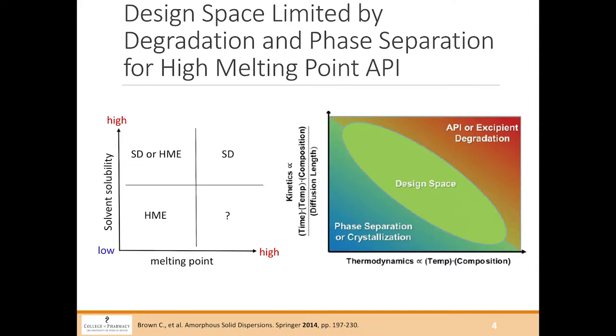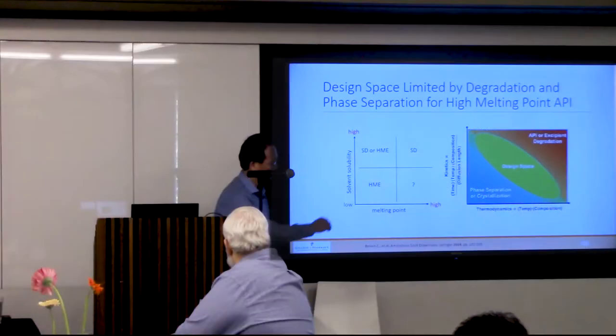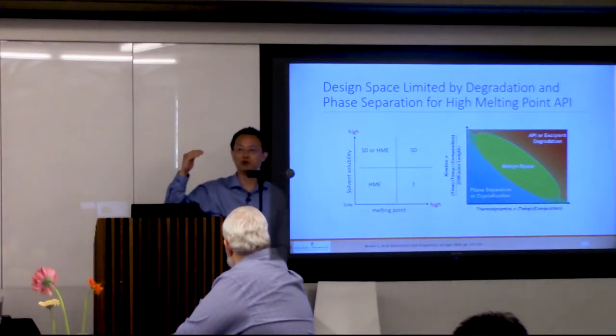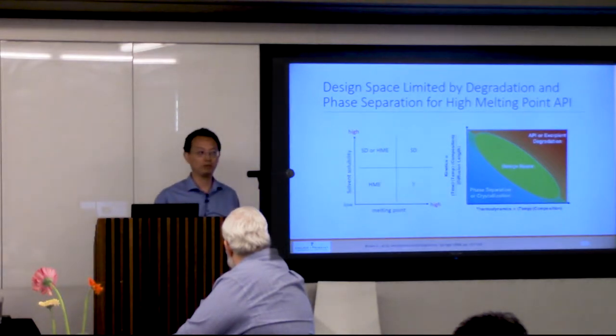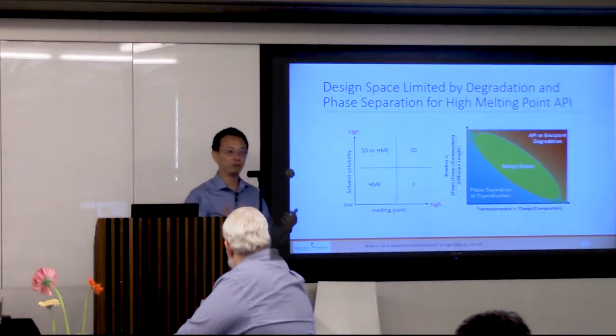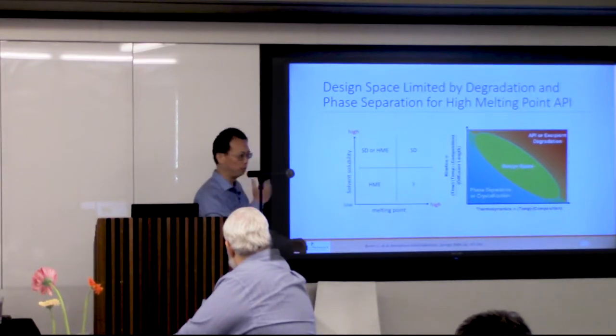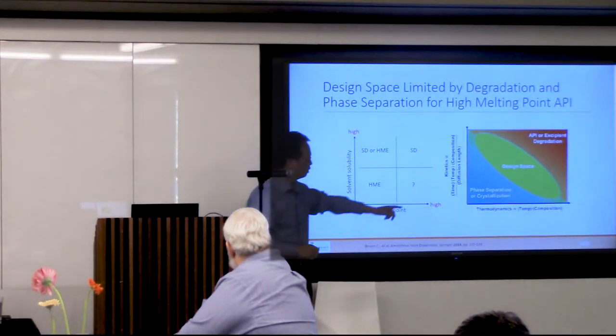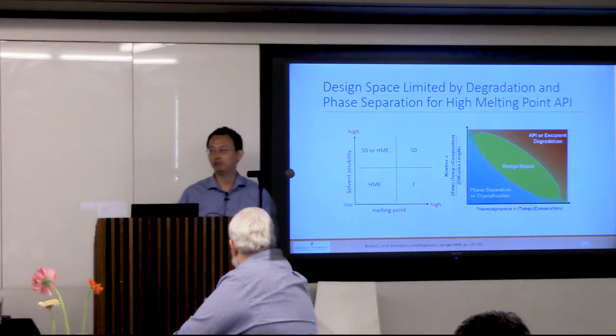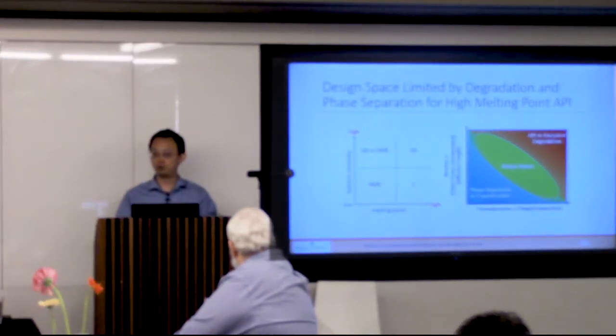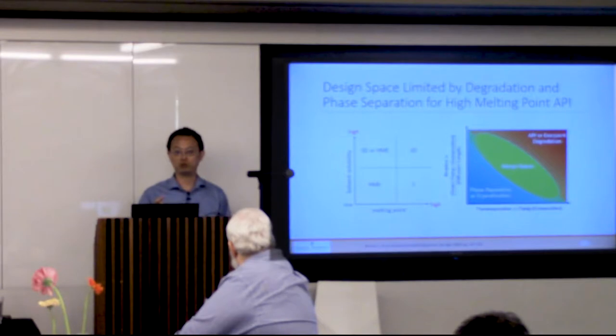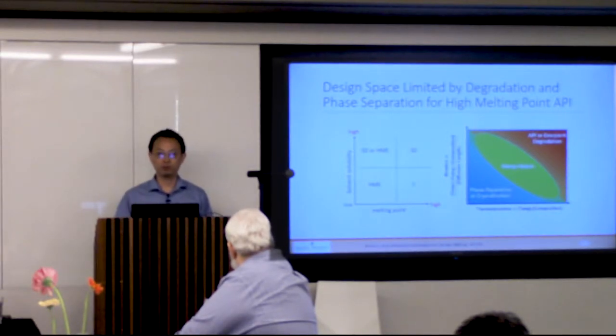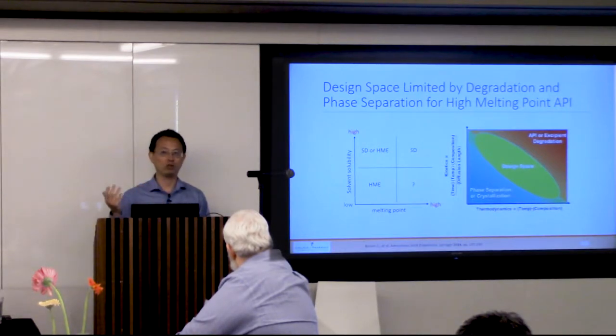There's a thermodynamic factor in the x-axis, and there's a kinetic factor. For the thermodynamic factor, you have to get a certain temperature. Otherwise, the drug is not going to dissolve in your polymer. You know? So if you know your drug and your polymer, you have to get a certain temperature from a processing perspective. The kinetic factor is because the drug has to dissolve in the polymer. And drug dissolving in polymer is nothing different from dissolving sugar in water. You don't have to melt sugar. If the drug really likes the polymer, you're going to dissolve the drug way before you hit the melting point of the drug.